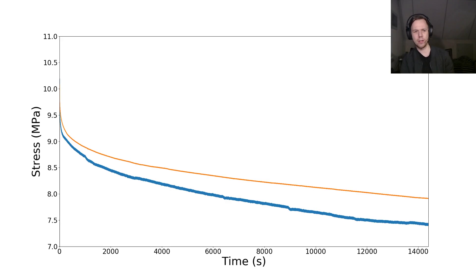So, moving on, we have a different experiment. In this case, the blue line is a sample of 20 square millimeters and the orange line represents a sample of 100 square millimeters. It's the same sample. It's just five times thicker. That's all that is. And what I'm trying to show here is that the creep that we have seen in the graph so far is really a phenomenon in the sample, and it is not an artifact of my machine.